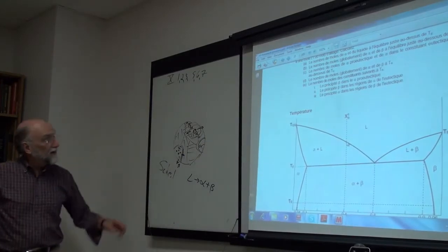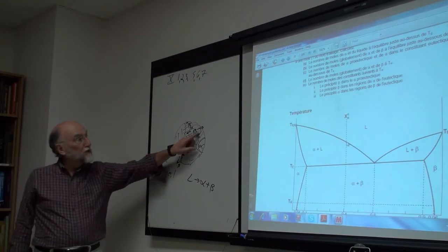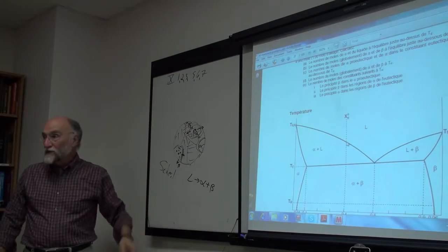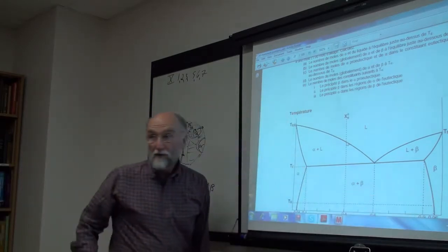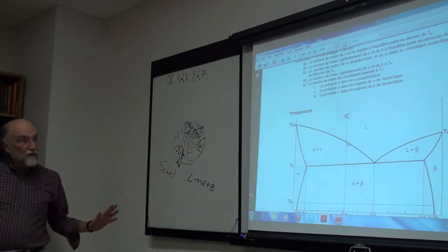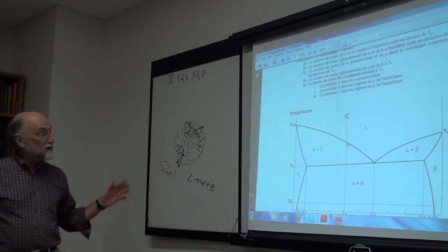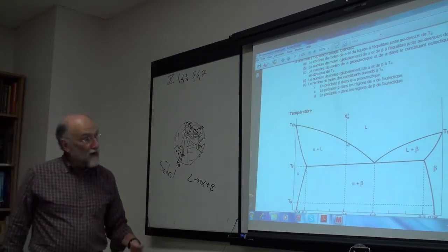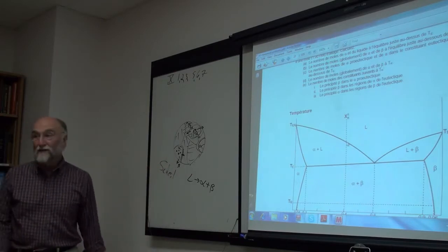Microstructurally now, it's very complicated. Now you have residual primary alpha with beta precipitates in it, you have residual eutectic alpha with beta precipitates, you have residual beta eutectic with alpha precipitates. But if the thing's totally at equilibrium, you still only have two phases. The lever rule is just a mass balance. Doesn't matter if it's mole fraction or mass fraction. But it assumes that all phases are homogeneous and the whole thing's at equilibrium. If you've got non-equilibrium cooling and you have concentration gradients, or phases are not there in their equilibrium amounts, then it doesn't work.